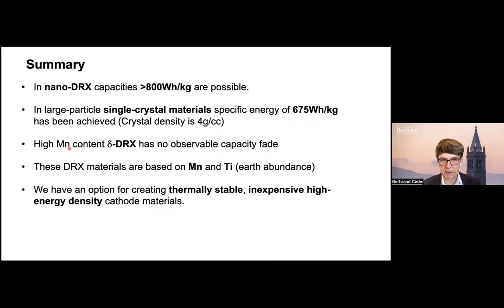We see no observable capacity fade, and in fairness, these are still half cells. We are about to start a full cell program in the consortium ahead of schedule. Our consortium was not supposed to do full cells, but because we feel we're ready, we will do that. There will inevitably come up the question of whether there is manganese dissolution or not. But the promising aspect is that these materials use only lithium, manganese, and titanium, and lithium is by far the most expensive element. So they are an option for inexpensive, high energy density, and maybe most importantly, thermally stable cathode materials.